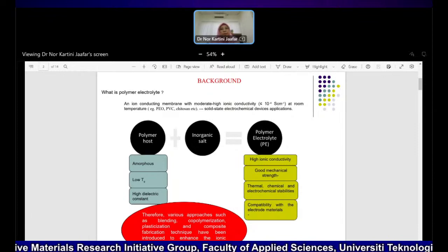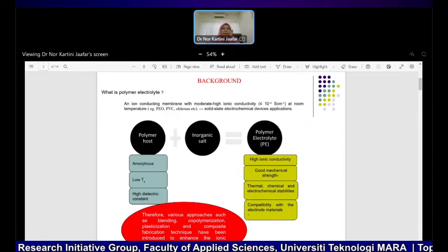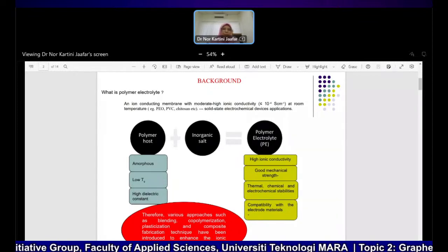So to have a good polymer electrolyte, the conductivity of the electrolyte must be more than power of -4 Siemens per centimeter at room temperature.